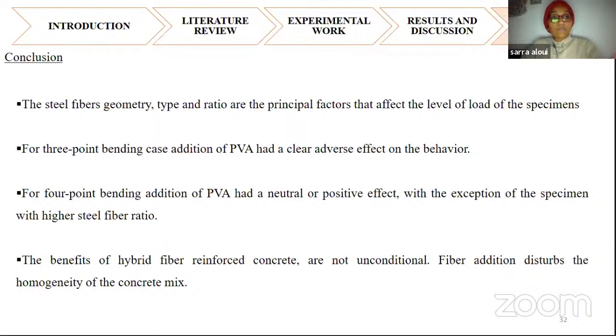But we can see here that for the 3-point bending test, the addition of PVA has an adverse effect. It always drops the maximum capacity of the specimen. But for the 4-point bending test, the addition of PVA has a positive or neutral effect, with the exception of the specimen with the higher steel fibers content, that is the SA4. But generally, we can say that the benefits of hybrid fiber reinforced concrete are not unconditional. The fiber addition can disturb the homogeneity of the mix design mainly.